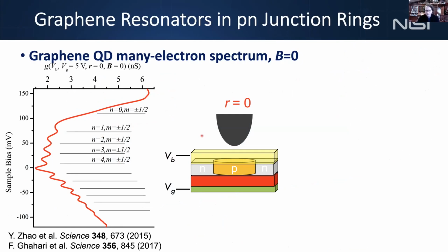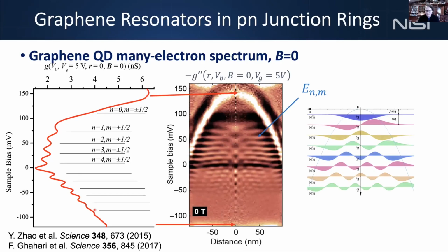If I move the tip horizontally, I can take spectra as a function of radial position and plot a new map where I combine all these spectra as a function of position, and I make a spectral map with distance on the bottom axis, okay? Here you see the harmonic potential, and now you see a whole bunch of modes here in the middle. So this is the complete wave function map of this quantum dot, which you can only measure because it's graphene and exposed at the surface.